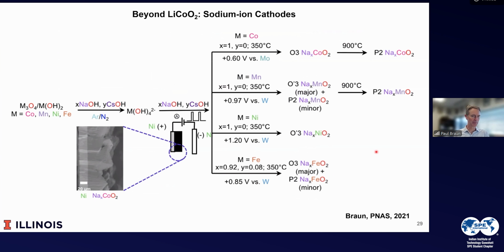Okay, let's talk about a few other chemistries here, and then we'll go discuss some about the solid state systems. So what I've talked to you so far about is lithium cobalt oxide. A few years ago, we published a paper on other sodium systems, and so we made the sodium cobalt oxide, sodium manganese oxide, sodium nickel oxide, and sodium iron oxide. These are interesting because of the interest in using sodium in place of lithium. So the cost of sodium, of course, is near zero. Lithium is more expensive. There may be reasons that sodium batteries are more stable. They tend not to have as good a kinetics, but still are of interest.